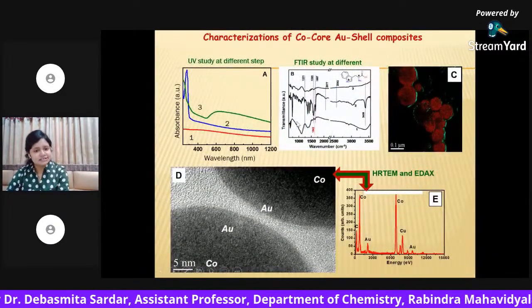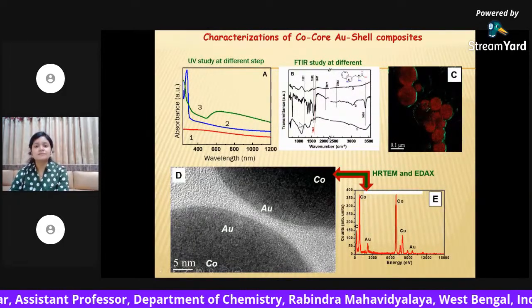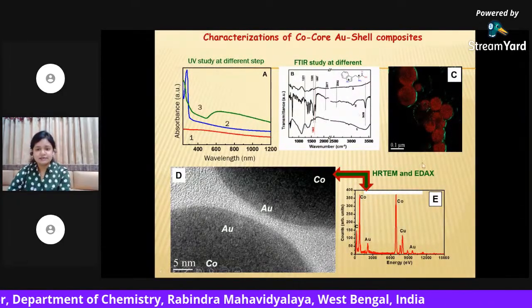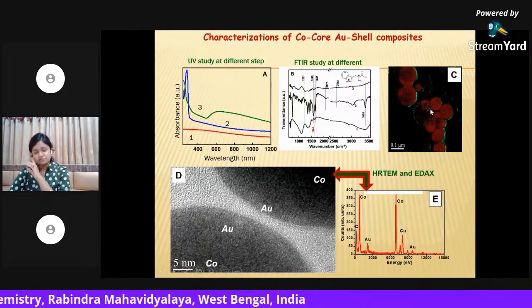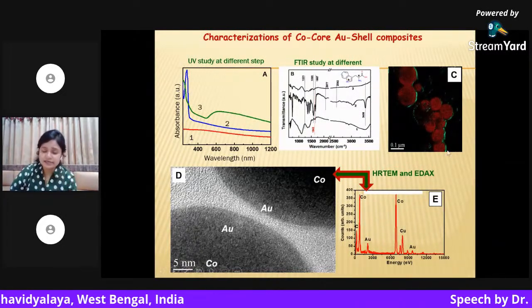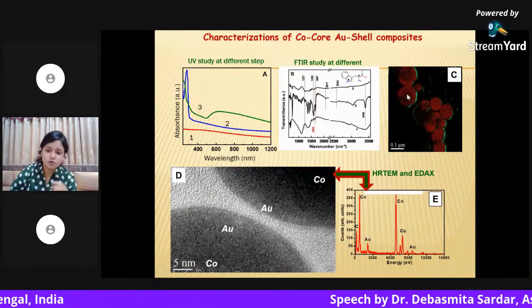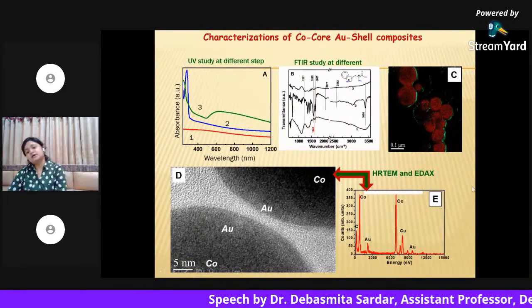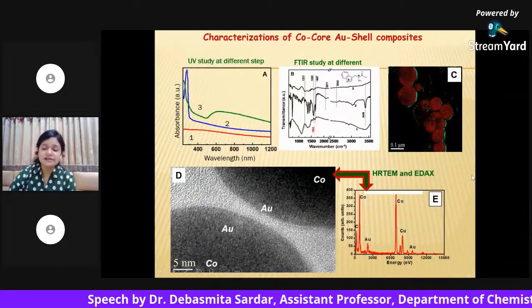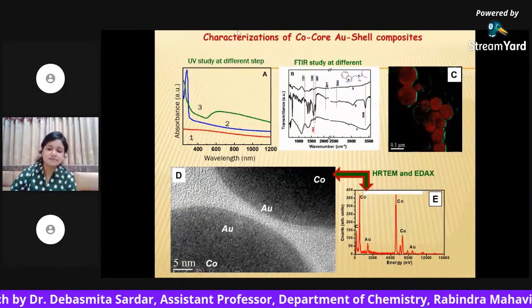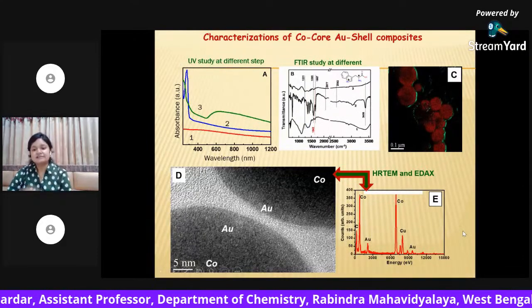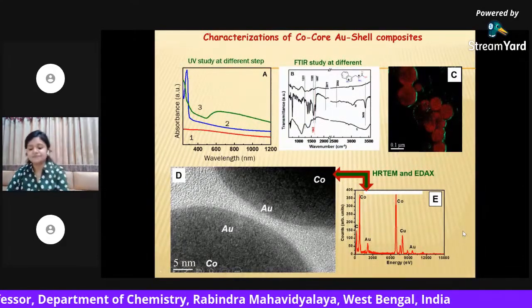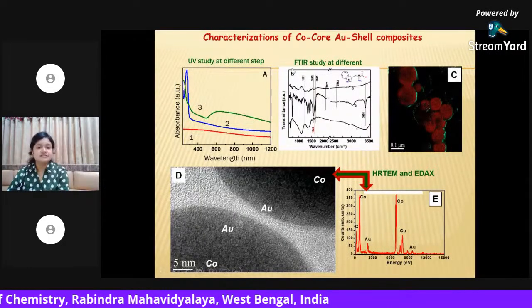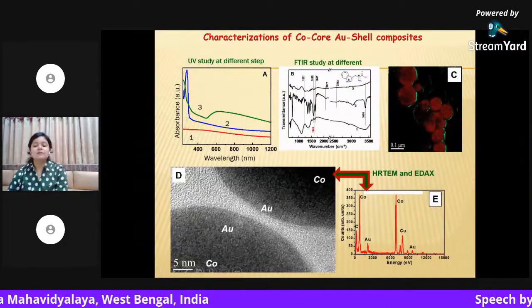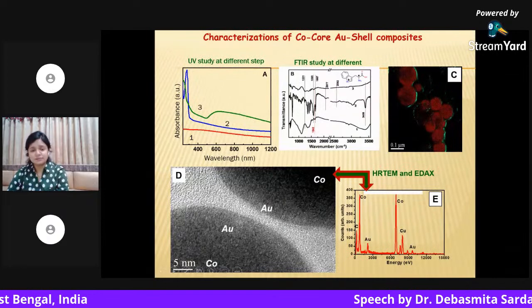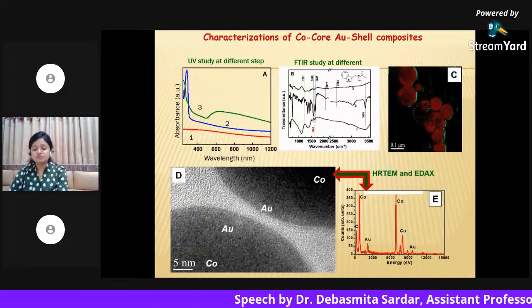So here are some characterizations to prove that this is a cobalt gold core shell composite. You can see the C picture looks like the cobalt gold nanoparticles. This is red, the cobalt portion, and the green is the gold portion. It is not a real color, it is just a color from the machine which reflects the metal portion. And the first one, UV study, FTIR study, all are proof of the cobalt core, gold shell composite formation.